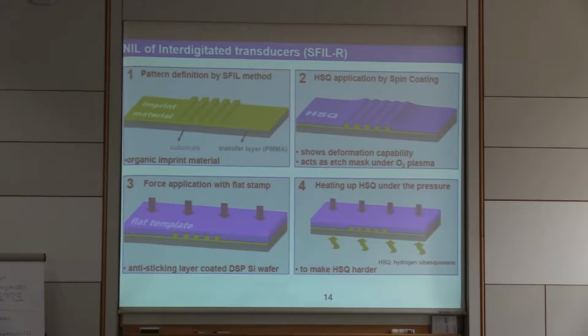And I will explain in a moment why this is beneficial. So instead of moving on from here and then just removing the residual layer, we first planarize with this HSQ, so spin on, and also we actually imprint with a flat stamp to further planarize this HSQ, so that we can get a very nice flat layer on top.